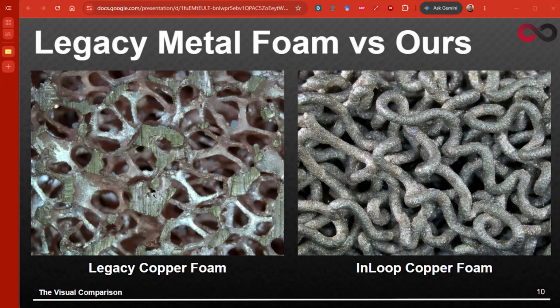It's interesting. One thing I will add actually is that while it sounds like you have some experience also with sintering solids with lattices, which we're also commonly compared to, we have found that because of our structure, that bent structure, like the actual buckled structure of the coils themselves, allow us to actually have greater resilience in surviving the shrinkage of debinding and sintering compared to structures that have straight links or solid sections where cracks can be very problematic.